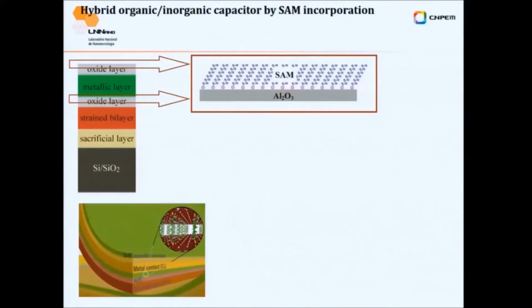So I asked what happens if you also add a self-assembled monolayer on top of the aluminum oxide layer? So basically you have a hybrid dielectric. We have inorganic aluminum oxide, but you also have an organic layer where you can change, for instance, the number of carbons. So we did that: on top of the aluminum oxide, we grew a self-assembled monolayer.